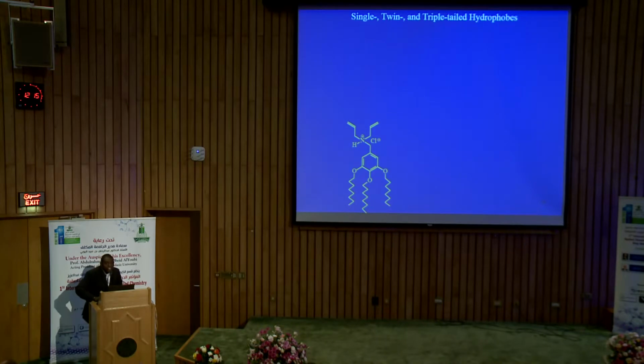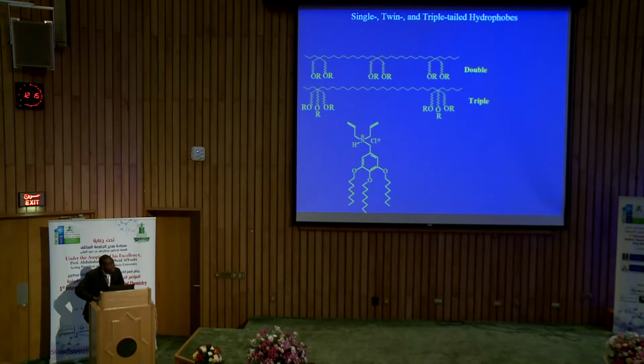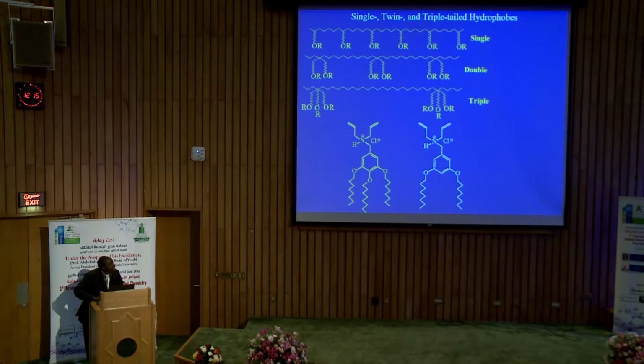So we decided to synthesize this particular monomer, a triple-tail monomer, so that we represent it as a triple-tail. But to have a meaningful assessment of what we are doing, we decided to synthesize a double-tail polymer for comparison, and of course, we also synthesize a single-tail for comparison. So what we do is to keep all these monomers. These are the 3 monomers: triple-tail, double-tail, and single-tail. But we try to keep the concentration the same.